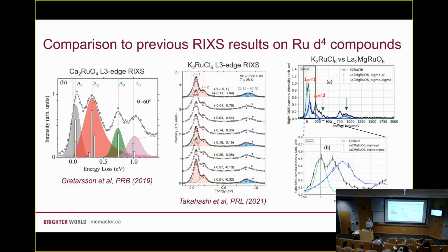Okay? So the good news, if this is what you're going after, is that this is one of the smallest measured spin orbit exciton gaps that we've got in one of these 4D transition metal systems. Small enough to the point where you might imagine being able to close the gap as a function of pressure or strain or some other tuning parameter.